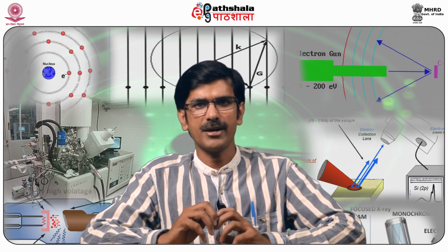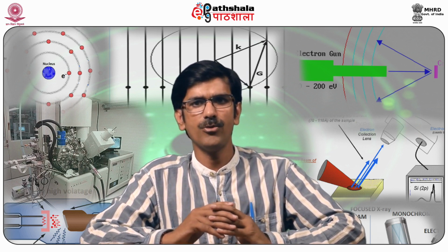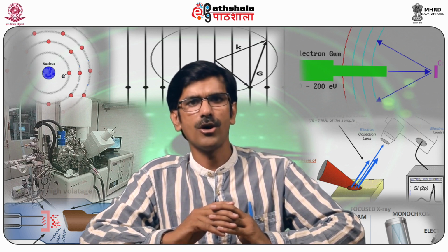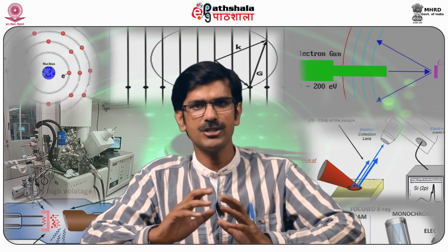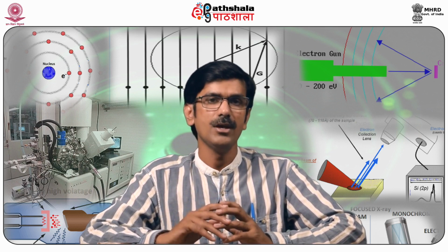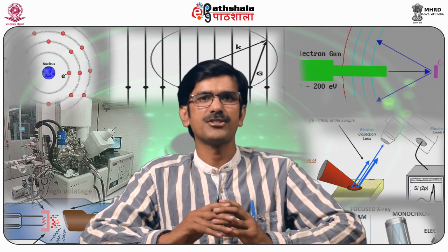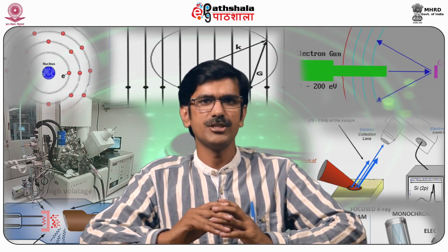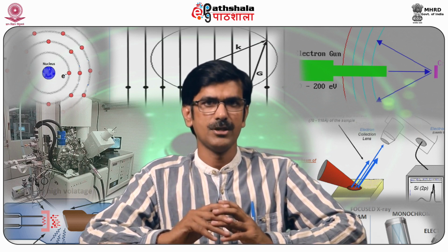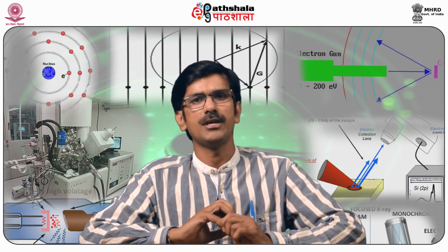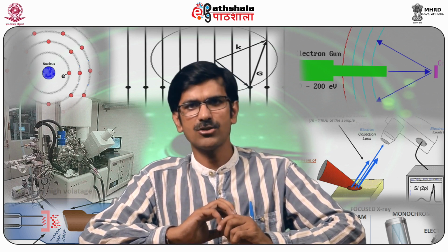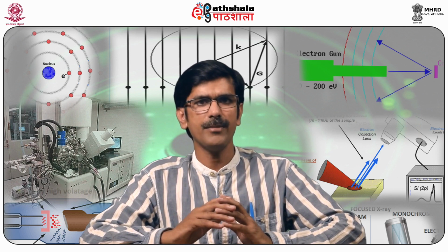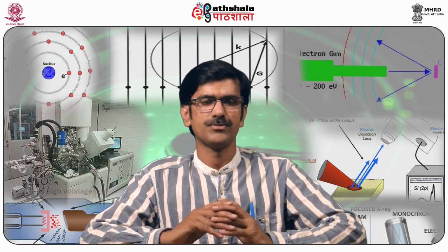Type 2 isotherms are characteristic of non-porous or macroporous adsorbents, and the knee in the isotherm indicates the completion of the monolayer coverage and initiation of multilayer adsorption. Type 3 depicts the unrestricted multilayer coverage. Mesoporous materials exhibit type 4 isotherm. The recommended adsorptive is nitrogen, except for the low surface area solids. For low surface area solids, generally less than 5 meters square per gram, krypton or xenon is used.